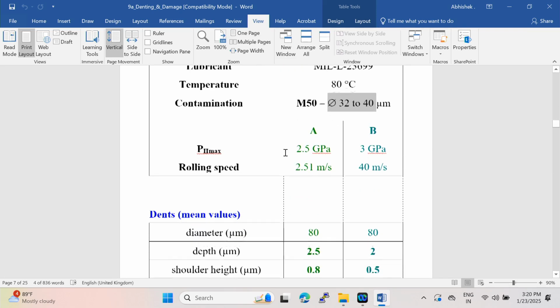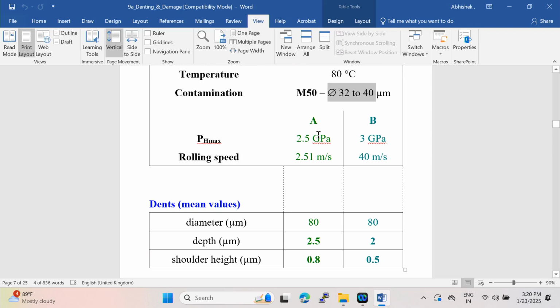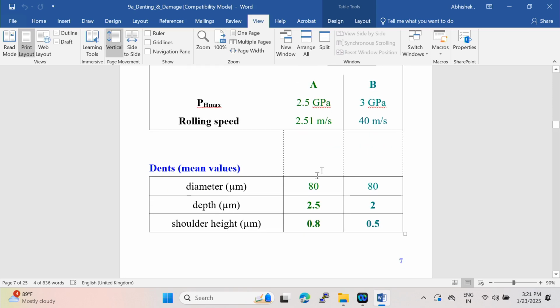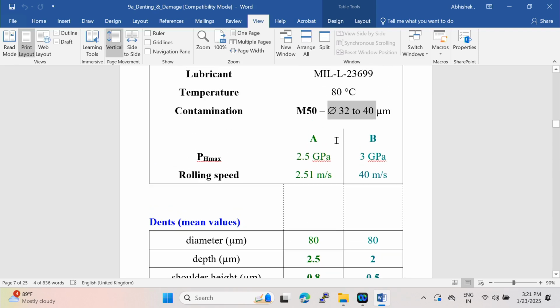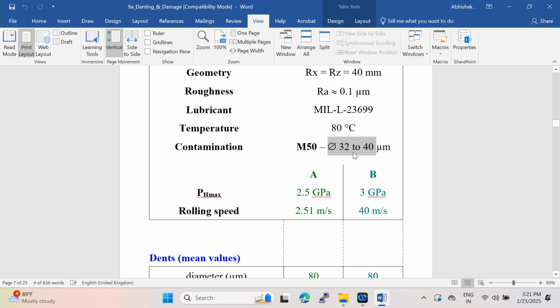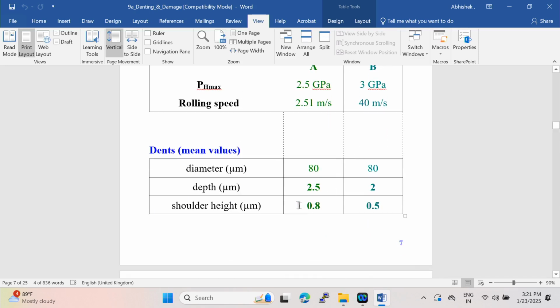And typically, we did two types of tests. Tests with 2.5 gigapascal at low speed and 3 gigapascal at high speed, 40 meters per second. And then typically these are the dents that we observe, the mean diameter of 80 micrometers, which is much higher than the initial diameter because it is deformed. The depth is 2.5 or 2 micrometers, which is very shallow. In fact, it's a very shallow dent. It's not 35 micrometers as I showed Monday or Tuesday. And the shoulder height is typically 0.8 micrometers or 0.5 micrometers. It depends on the speed.